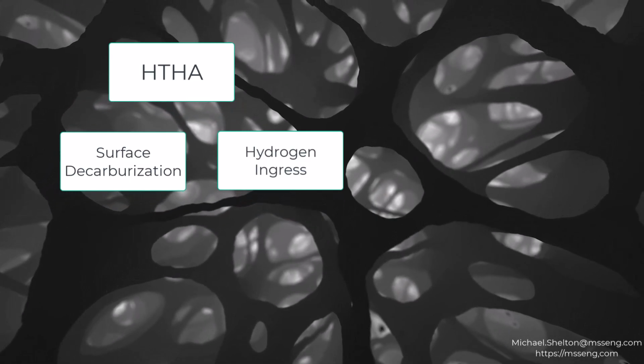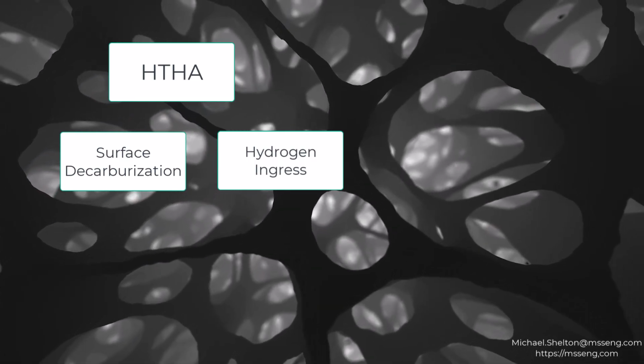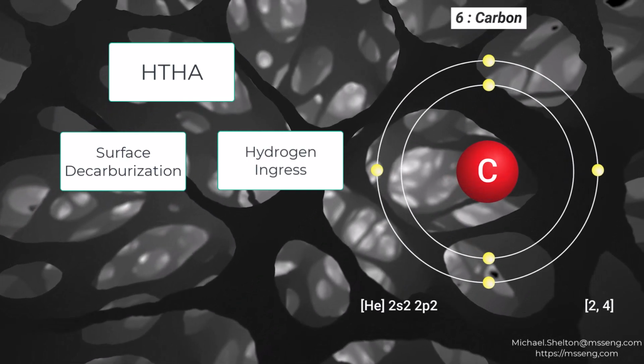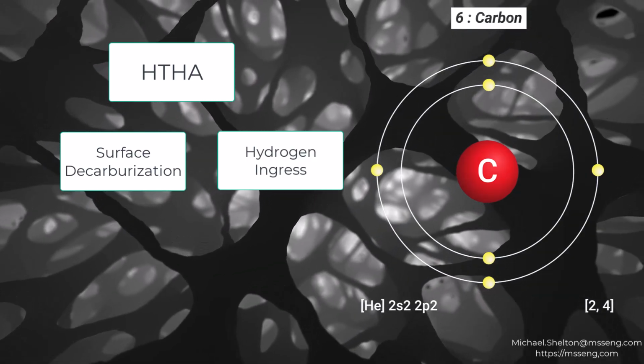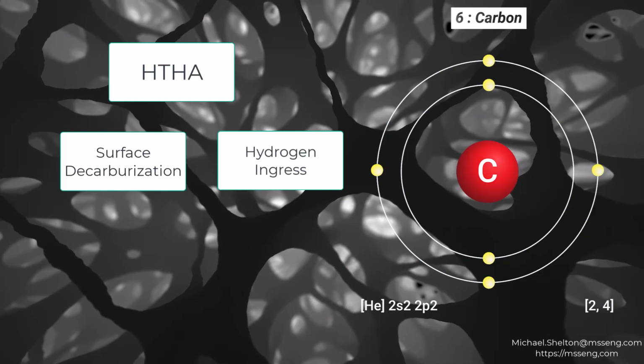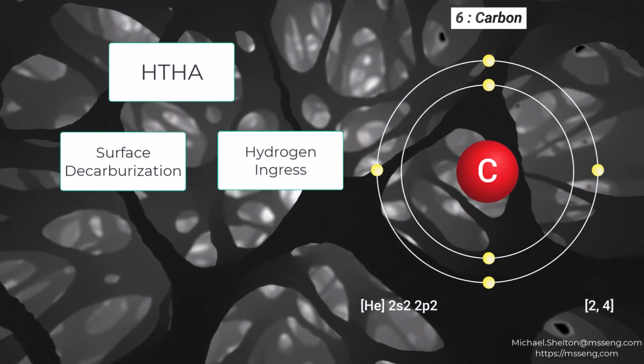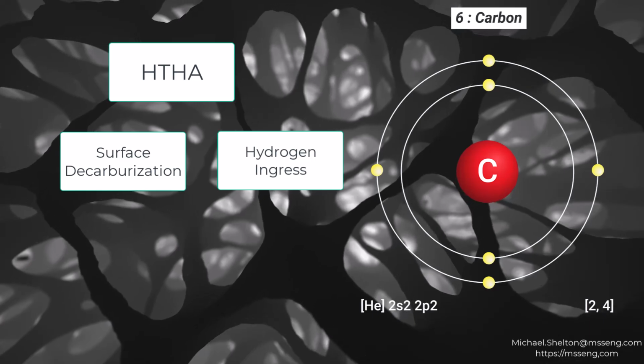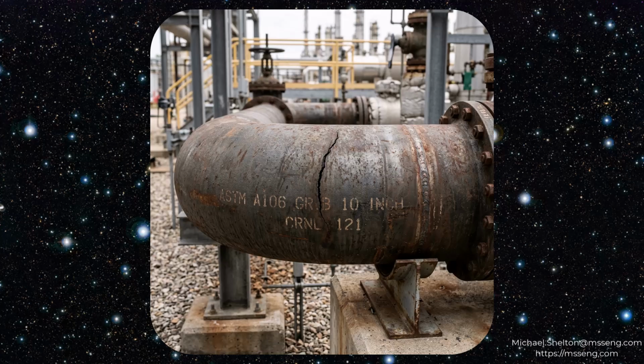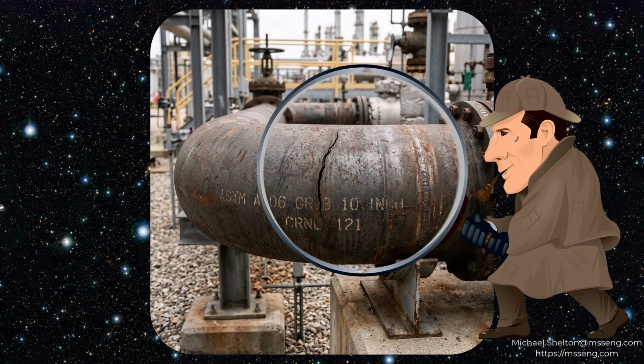These captured hydrogen ions may combine with freed carbon ions during the high temperature to form methane gas in much the same way as hydrogen ingress at lower temperatures forms hydrogen gas in the metal lattice. These metal dislocations, under the pressure of the accumulated methane, combine to form cracks which then lead to embrittlement. Therefore, early detection is critical for such operating scenarios that promote HTHA.